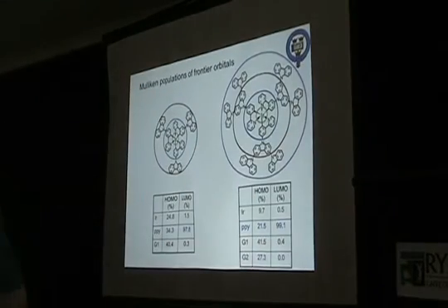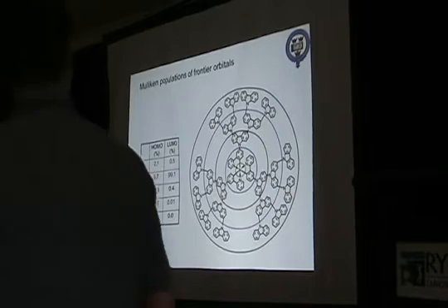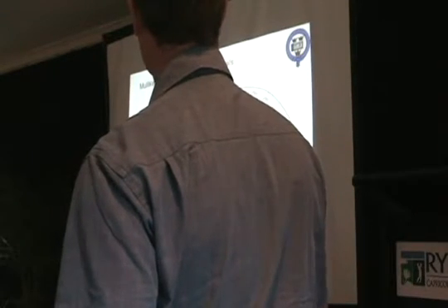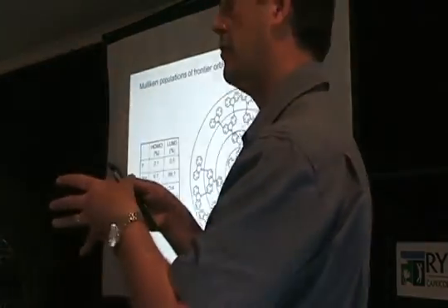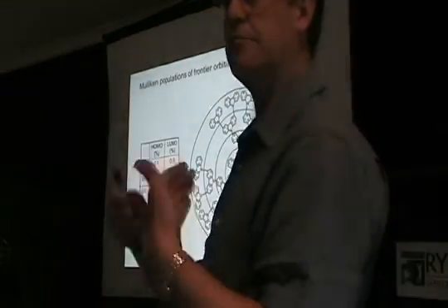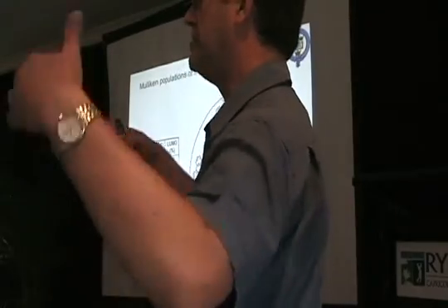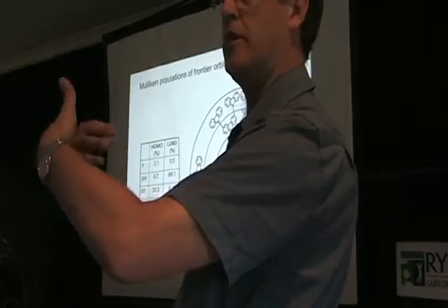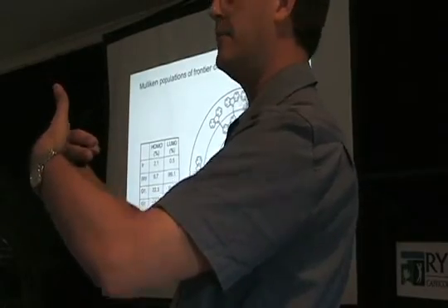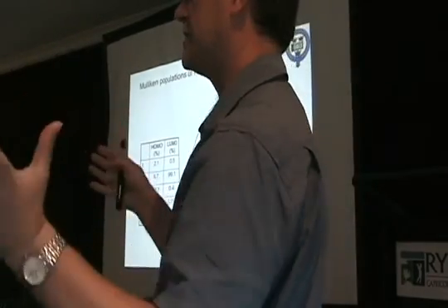And so that's fine. What about the third generation? Well, in the third generation, we still have a significant amount of highest occupied molecular orbital density on the outer carbazoles. In fact, we've got very little localized on the complex. So we can understand the improved charge mobility, because as you go up in generation, you have a lot more chance of overlap of highest occupied molecular orbital density, because you have a lot more units over which it's distributed.